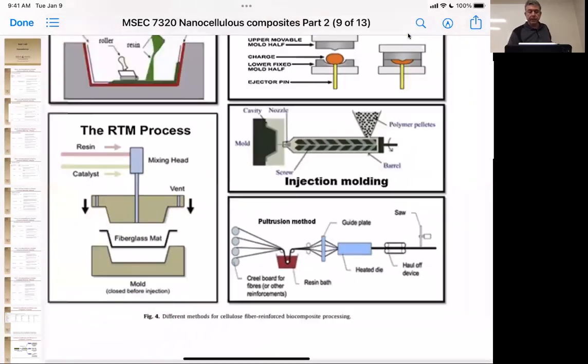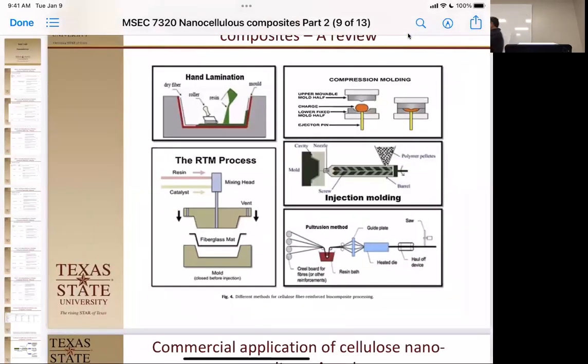There used to be a machine in England where they made composite cases for fuel tanks and helium tanks and everything like that. They called it the Dragon. The reason was that to get their matrix to stick to their fibers, they had to do a low oxygen flame plasma treatment immediately before. So literally there was flame shooting out of this thing right before it goes into the bath with epoxy, and then it's being wound on a multi-axis mandrel.